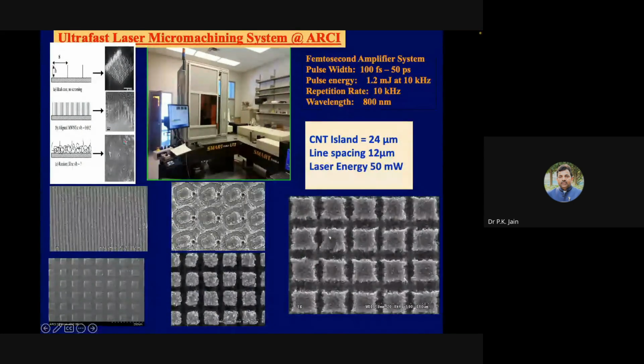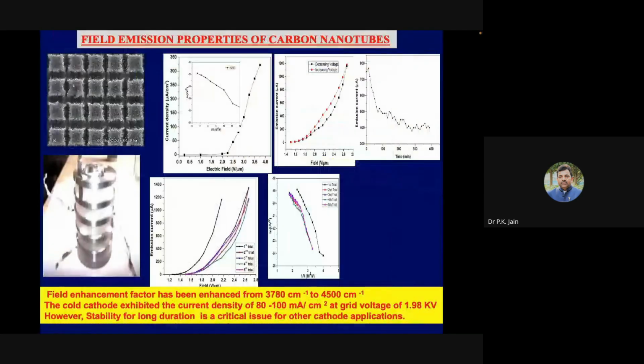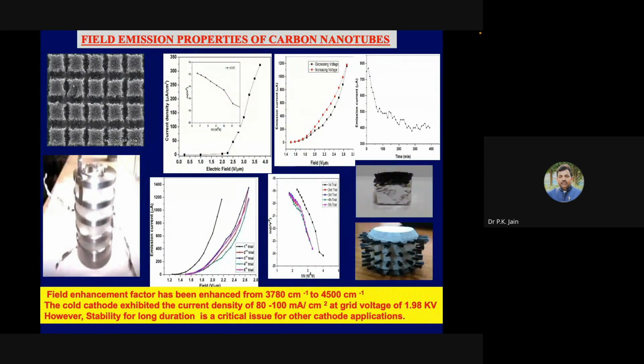So we have used our laser scribing, like laser micro machining, to scribe squares, so as to get more number of edges. And it was found that the emission is very, very high at low voltage. You can see the field enhancement factor has been enhanced from 3780 to 4500 per centimeter. So all these things are very high. Now we are working on a carbon fiber based field emitter for very, very high emissive activities.